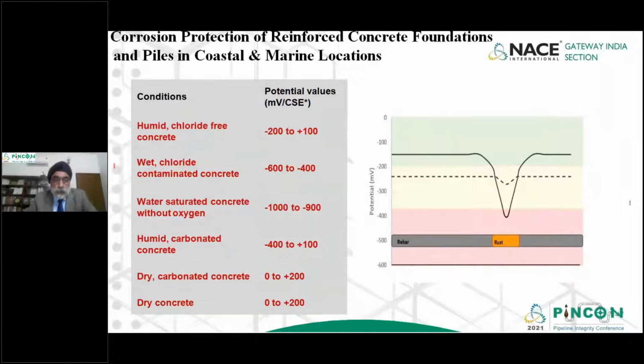Now, the way we have potential ranges of steel in soil, where we know that between minus 0.3 to minus 0.7, steel is corroding, but a potential of minus 0.3 volt in steel shows that the steel is cathodic, and minus 0.7 shows that the steel is anodic. Same way, by measuring the potentials of steel in concrete, we can find out what is the condition of the rebar in concrete.